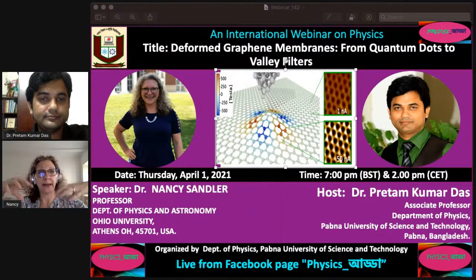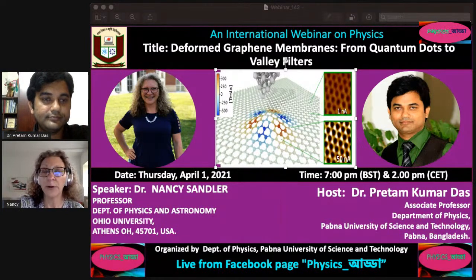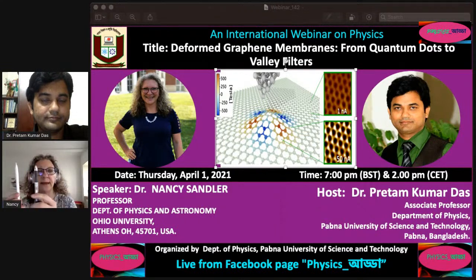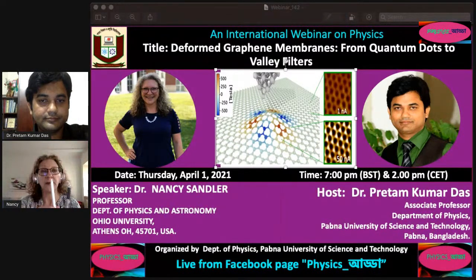Another way is to pattern the substrate, to have a substrate that is flat and to build little bumps, or people these days are putting periodically spaced cylinders, and they create like a bed with these cylinders, and they deposit graphene. And when the separation between these cylinders is big, graphene hangs in the middle.